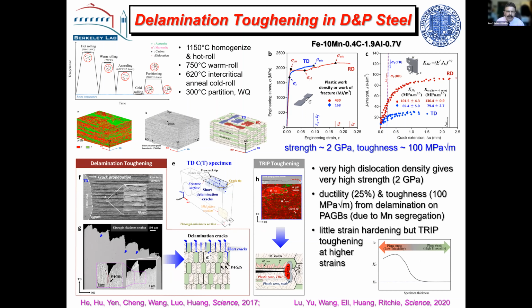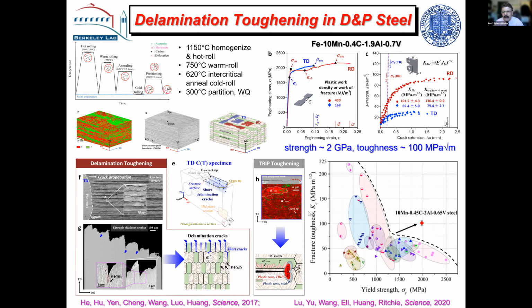Now, these delamination widths have got to put you in this region, so they've got to be the right size, and happenstance is okay here, but it still generates very high toughness, which is slightly increased by the TRIP effect as well. So I thought I'd throw that in because it's a different kind of mode. You can see here, this is a banana plot of toughness versus yield strength, and this pretty high toughness you can generate with these relatively cheap steels.